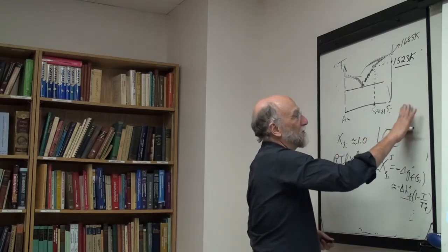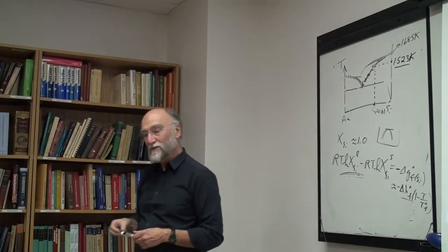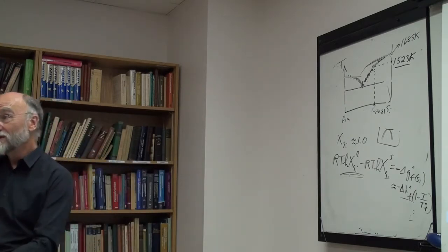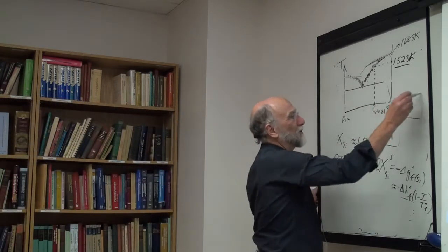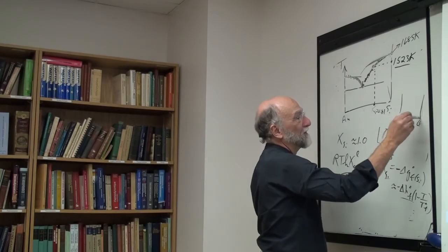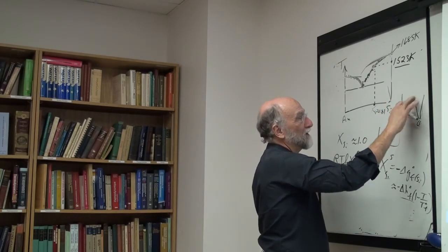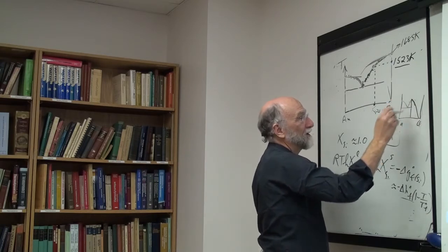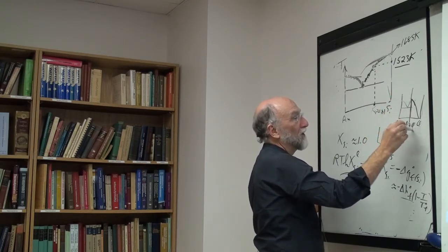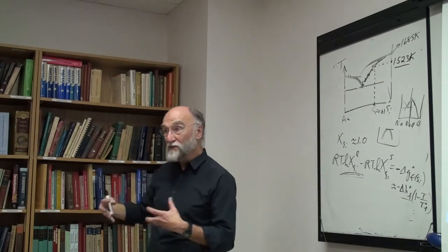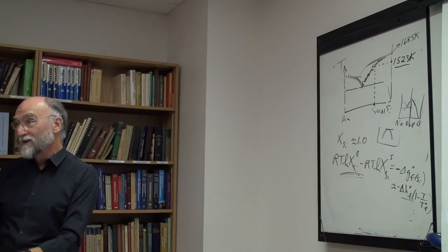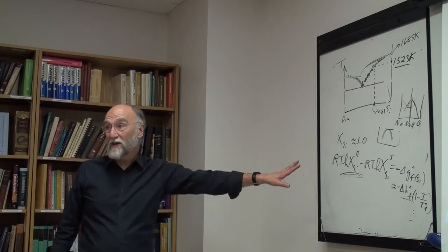If your limiting slope comes up, well, I won't get into that now. That depends upon it; for really highly ordered liquids, you're pretty close, but that's because the liquid is almost like a one component. In other words, if I were to draw the sodium chloride phase diagram, then your compound would be, to all intents and purposes, a peak like this, and this would be the sodium chloride diagram, and you could do the limiting slope. And that's only because the liquid is an ordered NaCl liquid. It's quasi-one. But that has to do more with the modeling than anything. But in principle, no, you can't. It only applies to the pure.